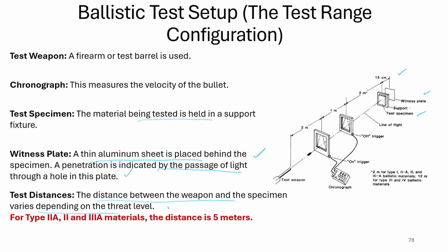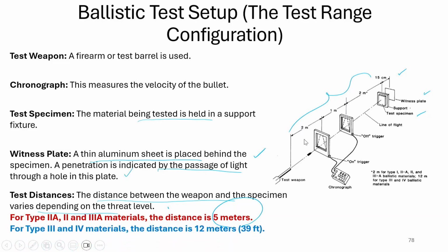Now, here you can see for lower threats 2A, 2, 3A, even 1, the distance is kept 5 meter. But for higher threats like 3, 4, the distance is kept 12 meter. So, the two distances are arranged for different threats, because for higher threat if we keep the 5 meter, then obviously there will be clear penetration, and in that case it is not possible. For higher threat we keep the distance higher.